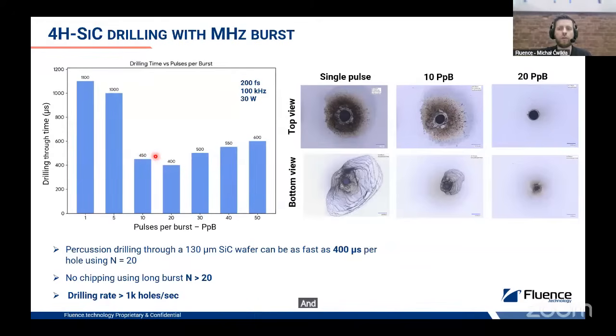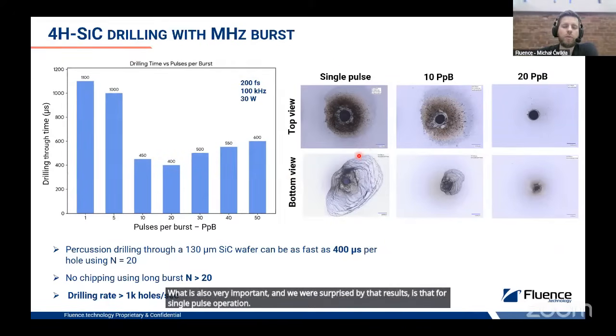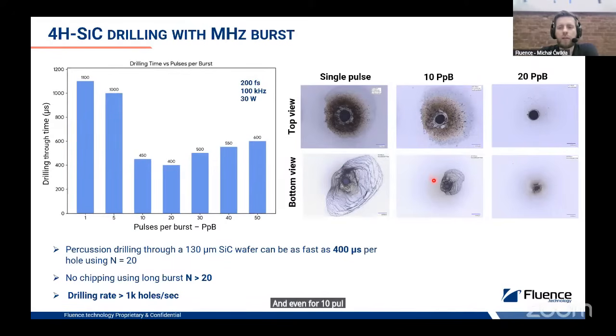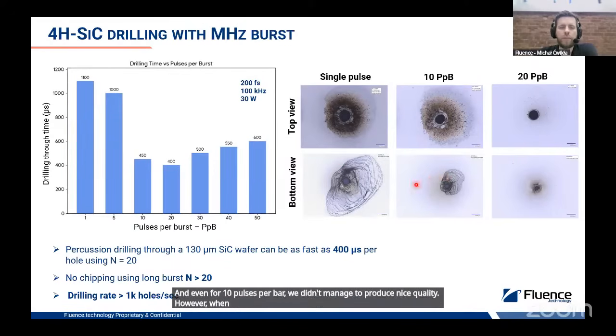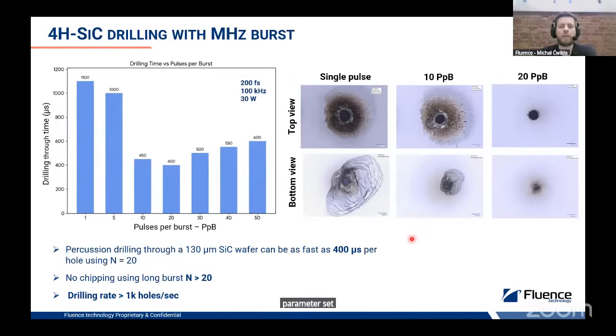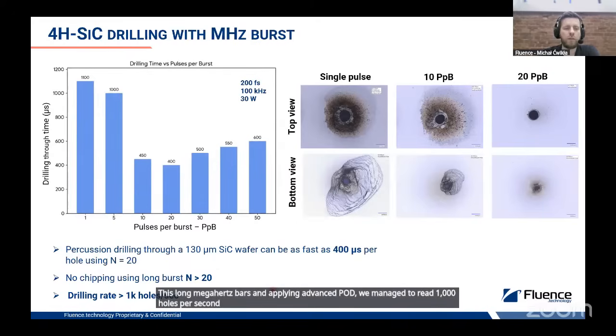And what is also very important, and we were surprised by these results, is that for single pulse operation, we didn't manage to produce a hole with good quality. There was always chipping of the bottom surface, material deposition, and some unwanted thermal effects. Even for 10 pulses per burst, we didn't manage to produce nice quality. However, when increasing to more than 20 pulses, not only was the drilling through time good, but the quality was the best for this parameter set. So this really shows the potential of these long megahertz bursts. And applying advanced POD, we managed to drill 1,000 holes per second in this 130 micrometer wafer.